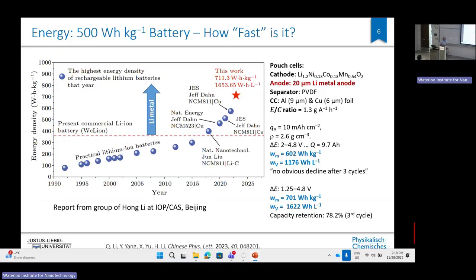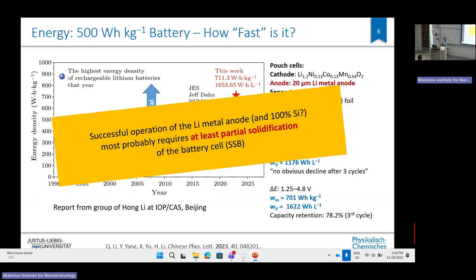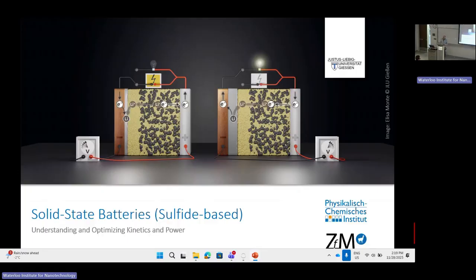But in principle, you can come to higher specific energies employing lithium metal. But my belief is that in a liquid electrolyte, it will be very difficult to safely employ a high-rate lithium metal anode, simply due to the dendrite risk. Metal deposition in liquid electrolyte will always lead to morphological instability, so you get the dendrite risk. And I think many people think that this can only be overcome by having a solid wall in the battery that avoids the dendrite risk. So the cells have to be partially solidified. Okay, and that brings me then to solid state batteries.